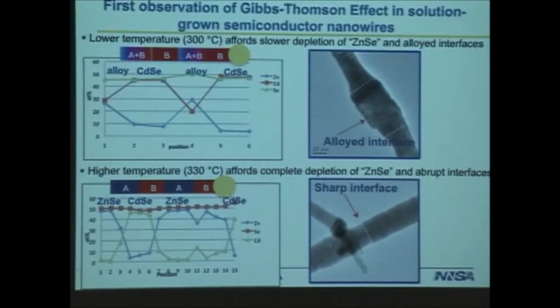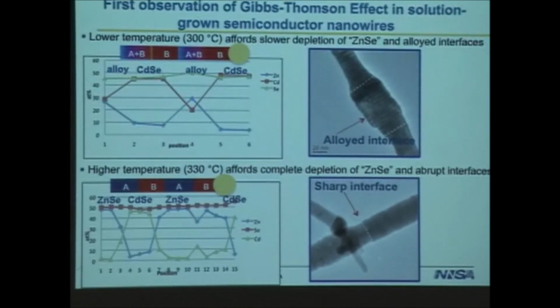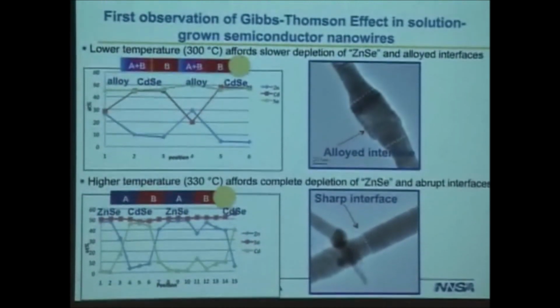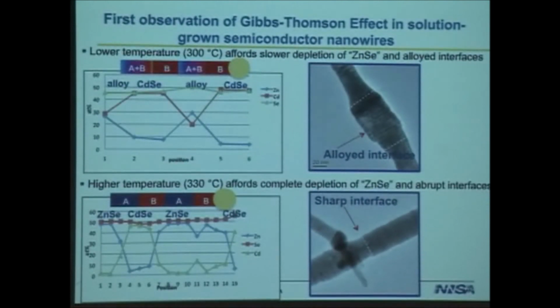from my perspective, do you see some twinning in that area? I should have brought it, I didn't bring this data. Okay. So the cadmium selenide is growing wurtzite, the zinc selenide cubic. And so they're meeting, my TEM expert is calling it quasi-epitaxial at the interface. So they're meeting at the lowest energy possible interface that they can.